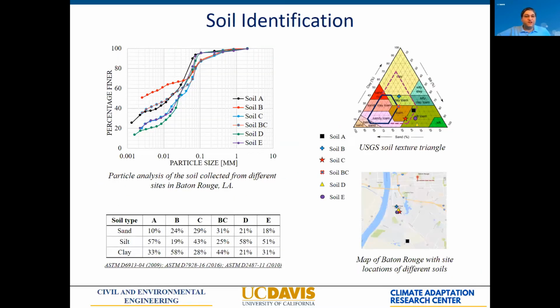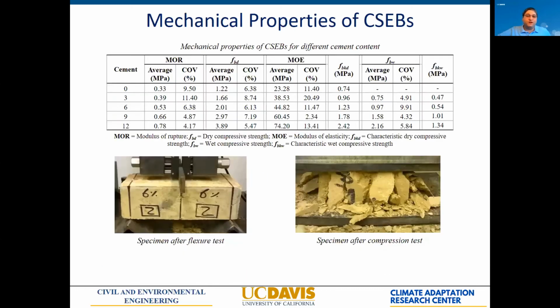We started with investigating the local soil. This is a soil that was collected around the Louisiana State University campus in Baton Rouge. As you can see, it is mostly outside of the optimal range of composition between silt, clay, and sand for earthen construction. So the need for some stabilization was clear. These are all of the different soils that we have used, with which we started fabricating our blocks. We investigated the compressive strength, the flexural strength, and all of the different properties with rigorous testing in our lab.